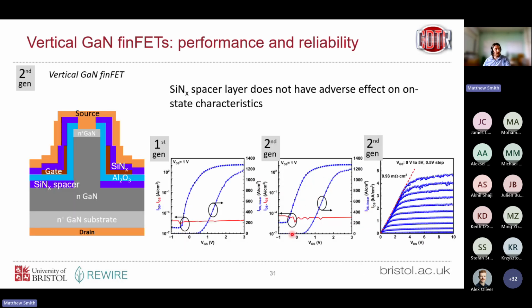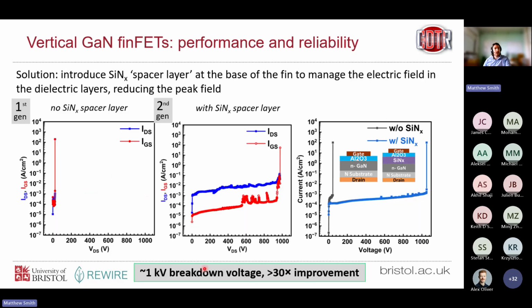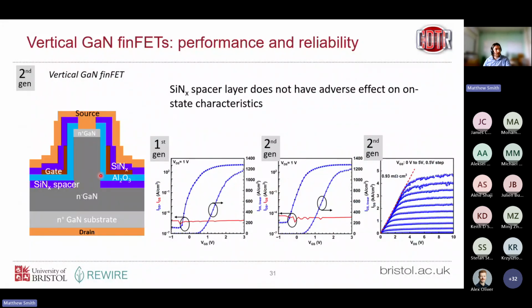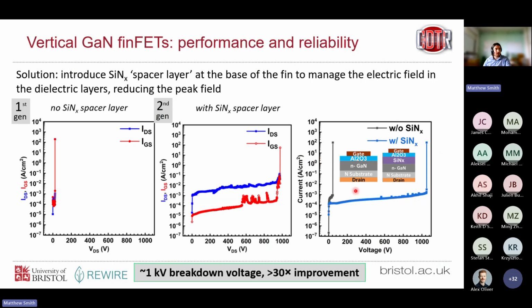So the second generation devices on state, they look very, very similar to the first generation. So adding this silicon nitride spacer layer didn't degrade our on-state properties. That's good news. But it massively enhanced our off-state properties. So we can see first generation breakdown, as we saw, it's sort of 30 volts kind of range. Second generation breakdown voltage, similar breakdown mechanism. It's this dielectric breakdown through the base of the fin, but we can see the breakdown voltage here is around 1 kilovolt. So something like a 30-35 times improvement when we add this silicon nitride spacer layer. And again, we confirmed that using our MISCAP test structures.